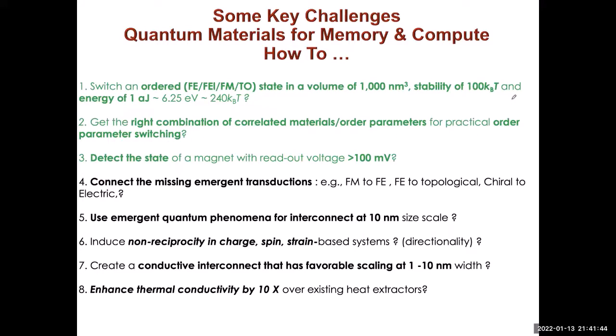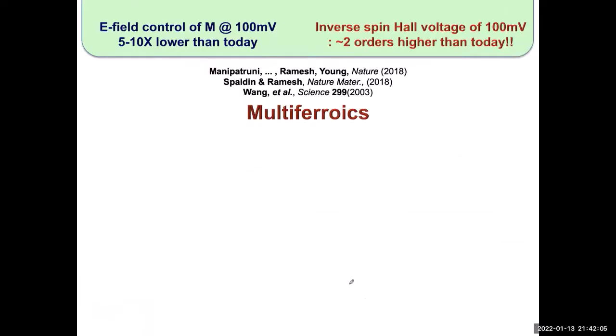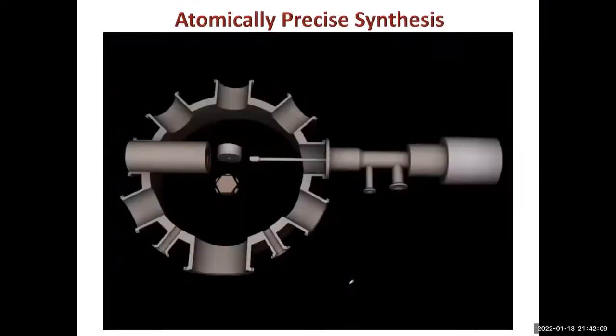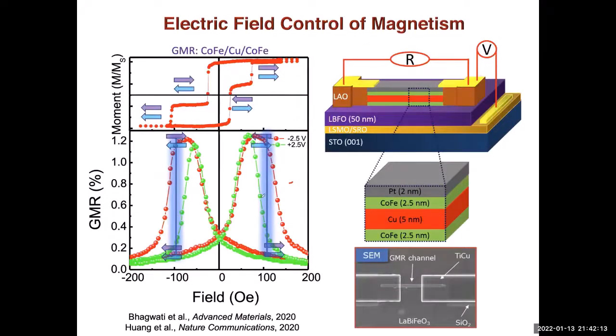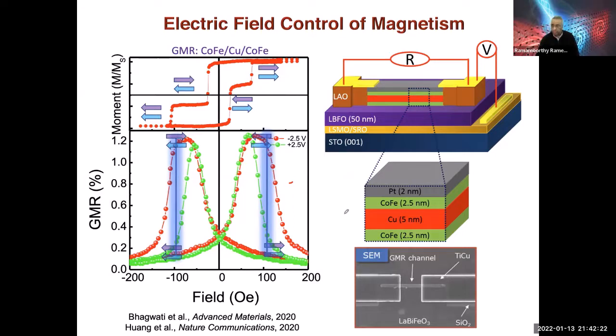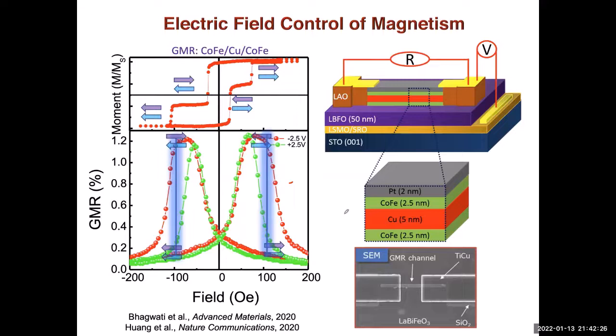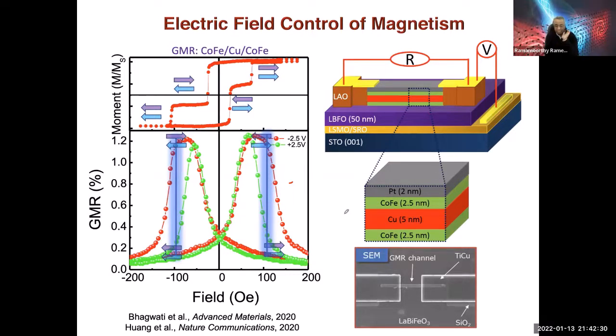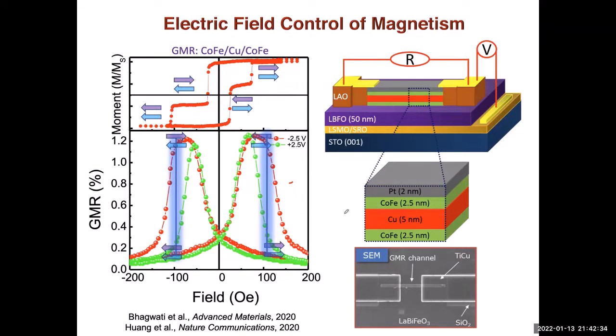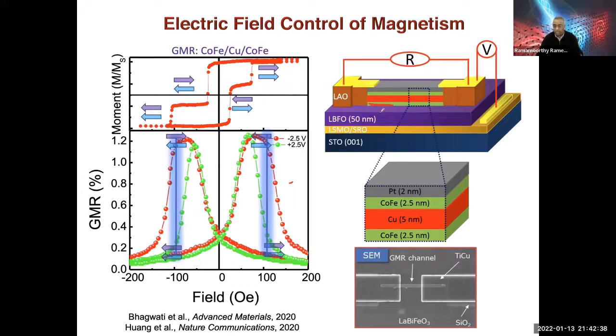I wanted to ask you a question regarding that electric field control of that spin valve structure, where this electric field is controlling the magnetization. Can you repeat again? Yes. I mean to ask about this spin valve control, where we are controlling the GMR. Here, are we controlling by the electric field? We are controlling the ferroelectric state of the LBFO. And by means of the magnetoelectric coupling, the magnetization is rotated in the bottom layer. And is that changing the entire resistance of the system? That is correct. Exactly. So this layer is the most important layer because its magnetization direction is going from this to this.